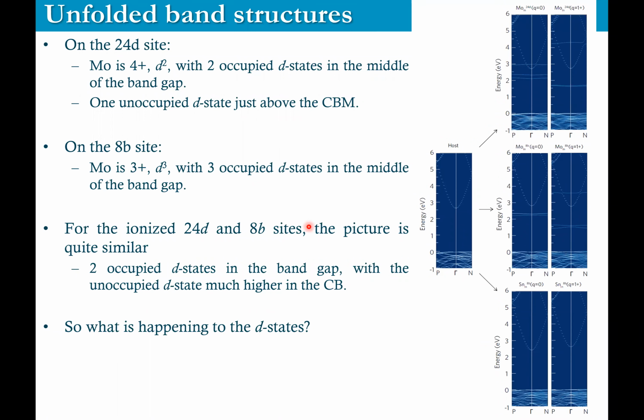On the 8B site, the picture is different. You have molybdenum, which is formally 3+ D3. So 3 occupied D states and no unoccupied state at the bottom of the conduction band. But when you ionize these defects, or when that extra electron is actually zipping around in the conduction band, the picture becomes quite similar. 2 D states are pushed downwards in energy or stabilized, and the 1 D state becomes unoccupied and is pushed higher in energy.